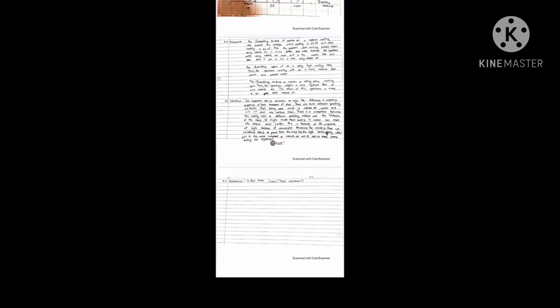Lastly, conclusion. This specimen was used to find out the difference in material properties from heat treatment of steel. There are three different quenching media being used, which are natural air, water, and oil, to cool the carbon steel. There is a comparison between the cooling rate in different quenching media and the hardness of the steel. It might show that cooling in water makes the carbon steel harder.